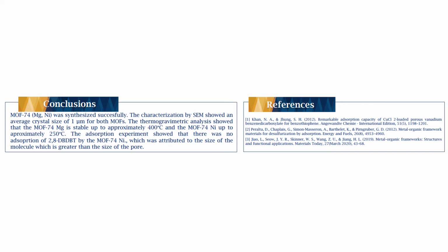MOF74 magnesium and nickel were synthesized successfully. The characterization by SEM showed an average crystal size of 1 micrometer for both MOFs. The thermogravimetric analysis showed that the MOF74 magnesium is stable up to approximately 400 Celsius and the MOF74 nickel up to approximately 250 Celsius. The adsorption experiment showed that there was no adsorption of 2,8-DB-DBT by the MOF74 nickel, which was attributed to the size of the molecule, which is greater than the size of the pore.